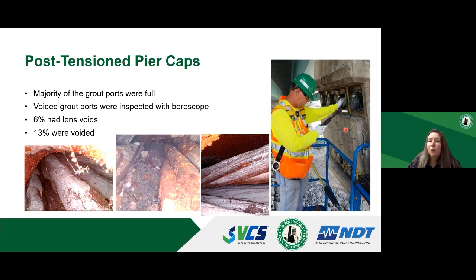This slide shows an image of the borescope inspection where the technician is feeding the borescope through the grout port. This was done on the grout ports that were empty. Obviously, we were not able to do it on grout ports that were full. And good news, the majority of the grout ports on this project were in fact full. In the grout ports that were voided, 6% had lens voids that are benign and don't put the strands at risk for corrosion, and 13% were fully voided. At the bottom of the slide, you see some typical images from the voided grout ports.